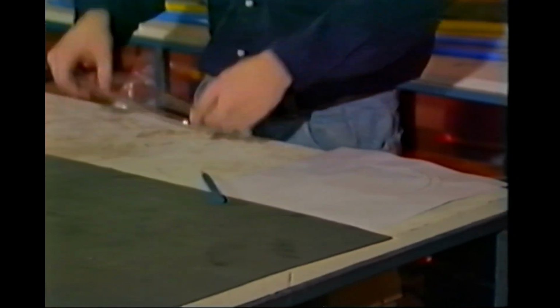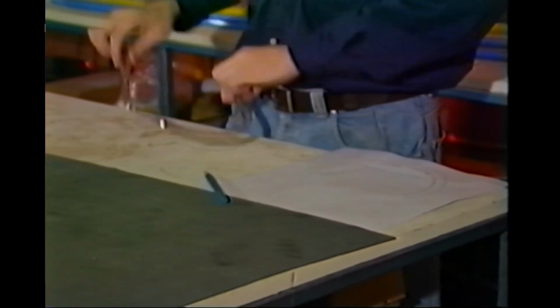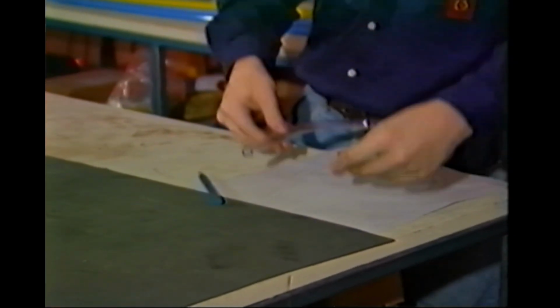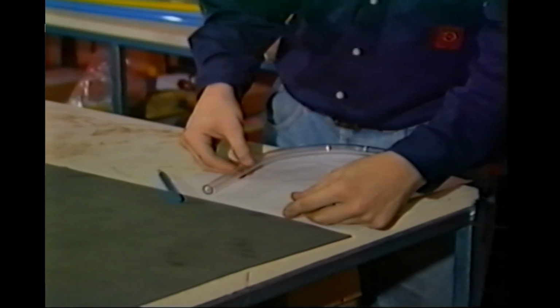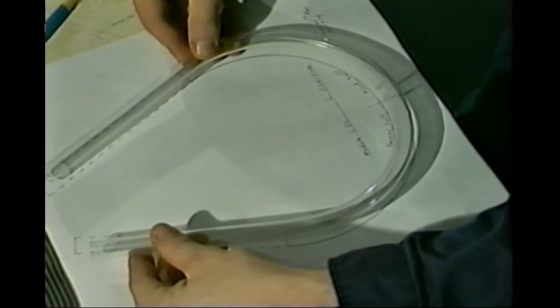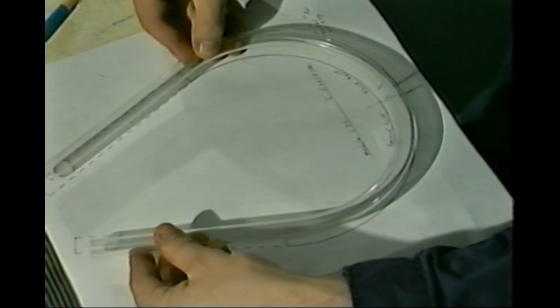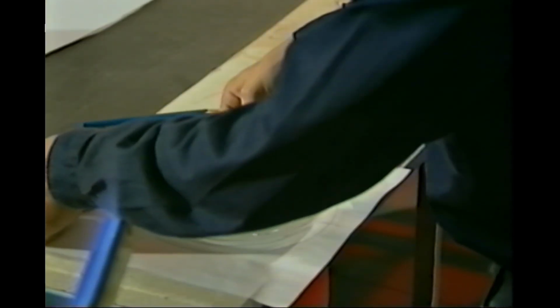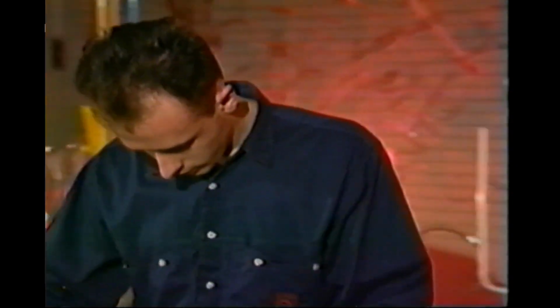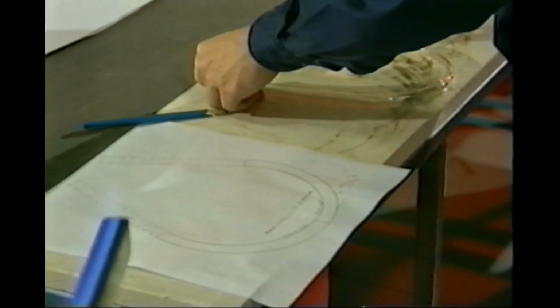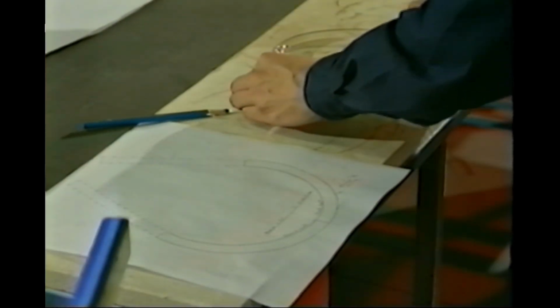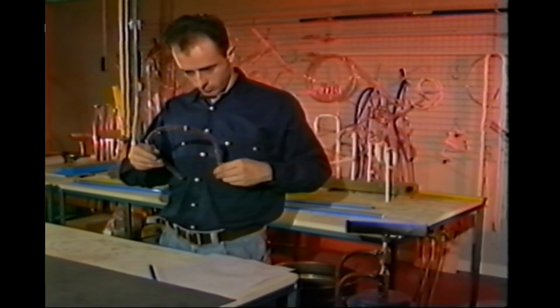Turn it over so that the second bend side corresponds to the left side of the C drawing. Move the tube quickly to the drawing, holding it above the drawing to stop it burning. Fit the cold first bend exactly to the right side of the drawing and adjust the still soft left side to achieve a good overall fit. Lastly, lay the curve on the bench top to flatten completely. Lift from the bench quickly and leave to cool down.